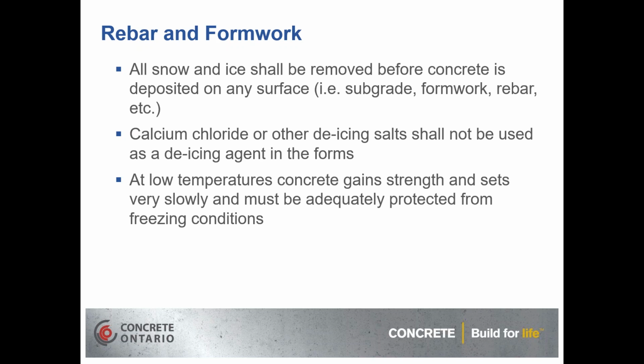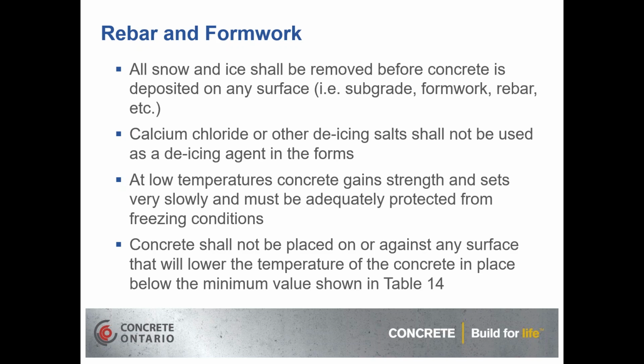What we do know through history is that at low temperatures, concrete gains strength and sets very slowly, especially if it's left unprotected to the cold ambient conditions. And because of that, it must be adequately protected from freezing conditions. Concrete that is allowed to freeze while in its plastic state can have its potential strength reduced by more than 50%, and its durability properties will be dramatically reduced. So it's best that we follow the proper practices to make sure that concrete does not freeze when placed in winter construction.